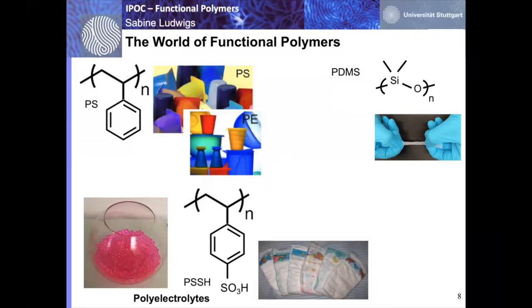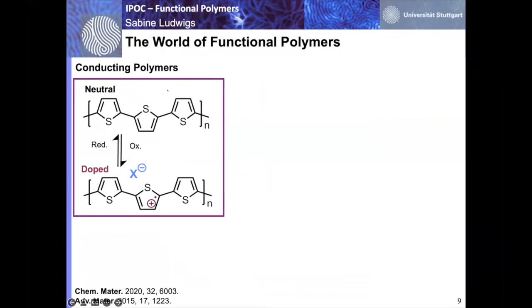So coming from these ion conducting polymers, as they can be termed as well, I'm much more interested in further going, and this is a class of conducting polymers. Conducting polymers, just briefly to their chemistry, that's a polythiophene backbone. So the main principle of a conducting polymer is that you have double and single bonds which are alternating, and you can use these so-called conjugated systems in a kind of doping way, where you take out electrons from this backbone and you put charges on this polymer backbone.